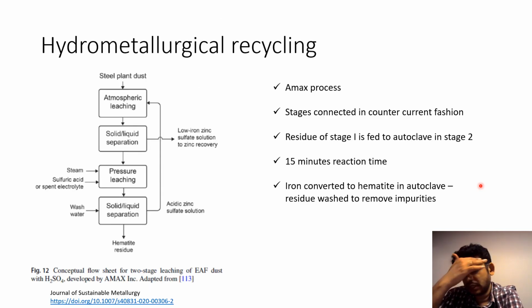So let's go. The first thing that I'm going to show you is a very simple Amax-developed hydrometallurgical process. Basically, what they do is a two-step leaching, and both stages are connected in a countercurrent fashion, so the things flow in opposite directions. First they do atmospheric leaching, and then the iron and other things from the waste go into the solution, and they do a pressure leaching step. The pressure leaching is done inside an autoclave at 200 and odd degrees Celsius.